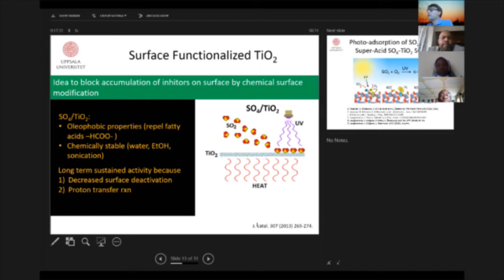So then I will turn to the next part of my presentation, which is surface functionalization. Here again, coming back to the theme of my presentation, the idea is to block accumulation of the inhibitor molecules and do it by chemical means. We have a methodology where we actually prepare a film. We can do it with the methods I just explained, sputtering, or it can be wet chemical. And then we have a process where we photoabsorb SO2 molecules, or actually other molecules of interest. And these are further reacted to sulfates on the surface, and thus very strongly bonded. So you cannot wash them away or even sonicate them away or with ethanol cleaning, they remain.